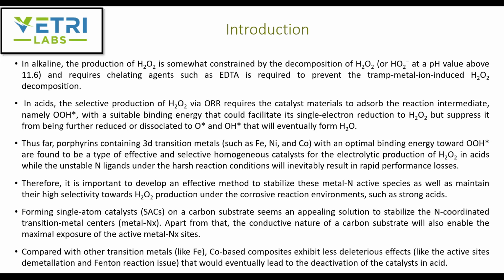The best approach is forming single atom catalysts on a carbon substrate to stabilize these nitrogen coordinated metal centers, called metal-N-X. Apart from that, when you use a carbon substrate, you have a conductive support, which will enable the maximum exposure of your active metal sites. And among the other commonly used transition metals, cobalt-based composites exhibit fewer deleterious effects, like active site demetallation or the Fenton reaction, which would eventually lead to the deactivation of the catalyst in acid.